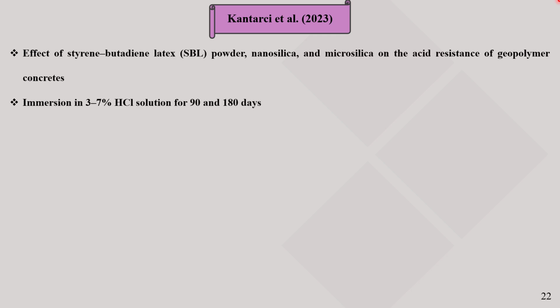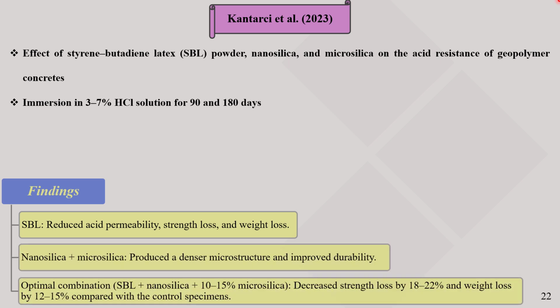Finally, Kantarci et al. studied the effects of styrene-butadiene latex powder, nanosilica, and microsilica on concrete strength in acidic environments over 90 to 180 days. They found that styrene-butadiene latex powder reduced permeability against acid, and both nanosilica and microsilica densified the structure and enhanced durability. The graphs from these experiments are also presented in this section.